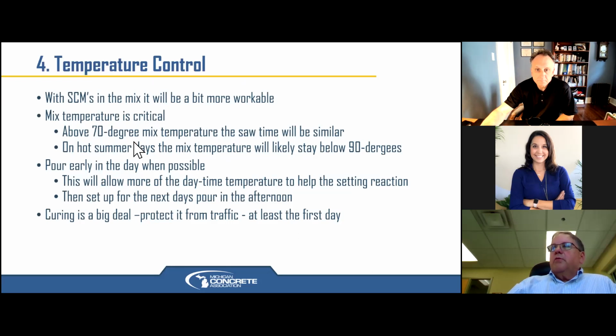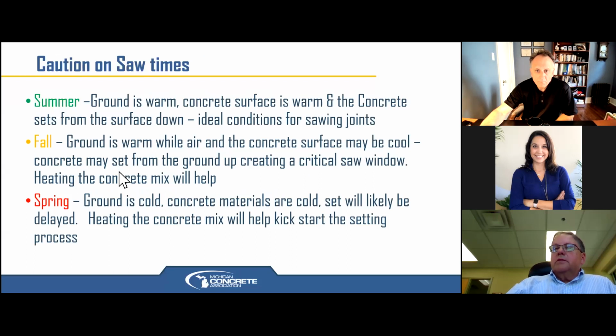But if we pour concrete out at 50-degree weather with 50-degree mixed temperatures, it's going to lay there quite a bit longer in the fall or in the spring before it sets up enough. And so it's important that we get our mixed temperature right, be very much more cognizant of the mixed temperature with these low carbon mixes. And by the way, curing is a huge deal. We have to keep that water in longer so that reaction can continue to take place.